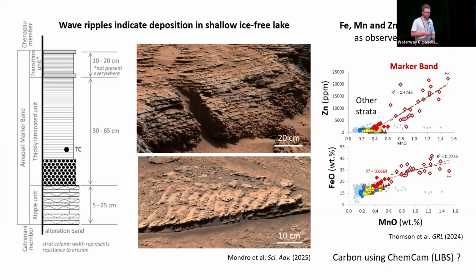And in terms of composition, this is the chemical data we were able to derive. This is from APXS. So the bulk of those targets really show, in red here, enrichment in iron, quite high, above 35%, and in zinc and manganese. So there is something standing out here.